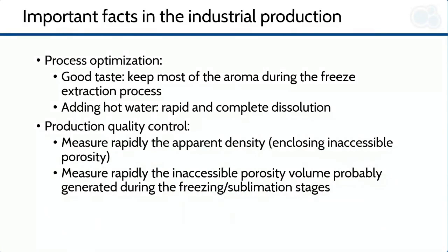Important tasks during instant coffee production are to provide coffee with a good taste and to rapidly and completely dissolve the coffee powder when added to hot water or milk. These features are strongly related to the microstructure of the coffee granules: their size, porosity, density and surface area. In production quality control, it is necessary to have a rapid method to measure these important parameters. Open and closed pores might influence the aroma and the speed of dissolution. Thus, it appears quite important to have a reliable and possibly rapid analytical method to characterize the coffee granules.